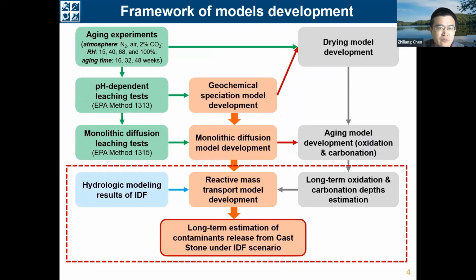And this is a framework for the models' development, starting from the aging experiments. The aged sample was then used to conduct different leaching tests, including the pH-dependent leaching test and the monolithic diffusion leaching test. And the test results are used to develop different models, including the geochemical speciation model, the monolithic diffusion model, the drying model, the aging model, and finally the reactive mass transfer model.